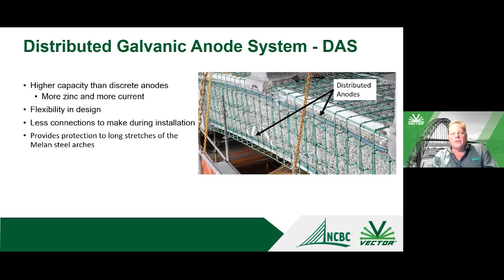So a lot of thought was put together for how to extend the life of the structure from a corrosion standpoint as well. And you see in the areas where you have basically concrete damage and concrete removal from the corrosion, the frame here was coated. So the white here is the existing coating. There was a reinforcing encasement around that.